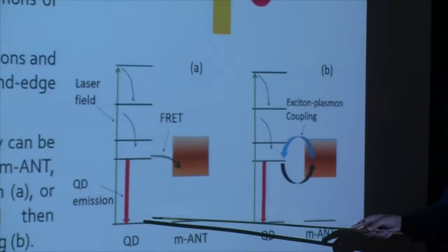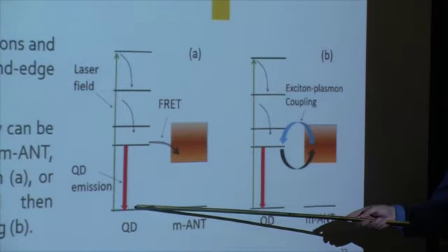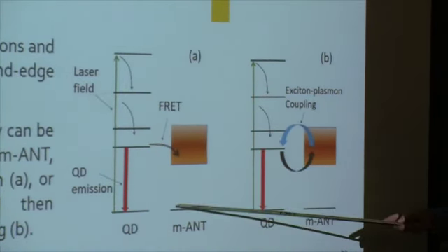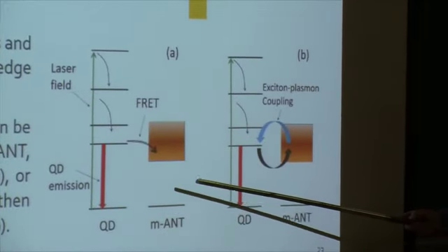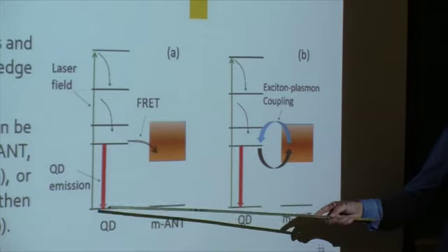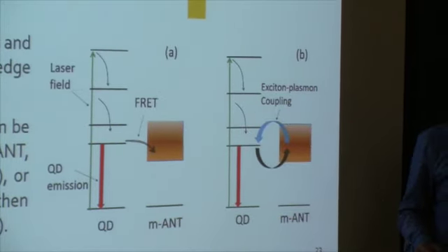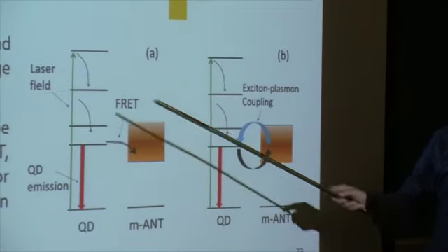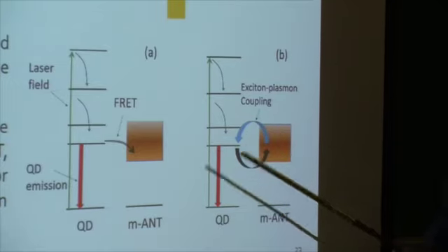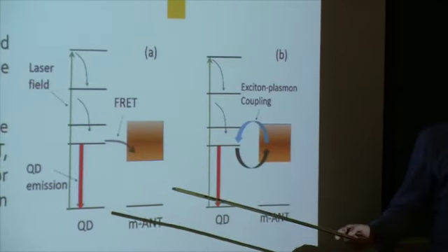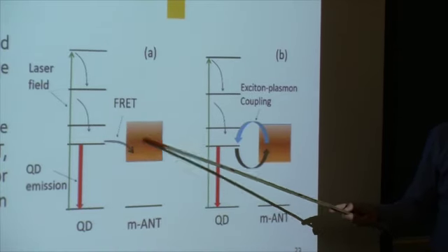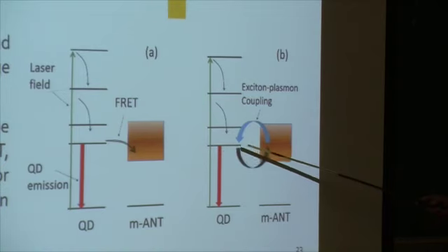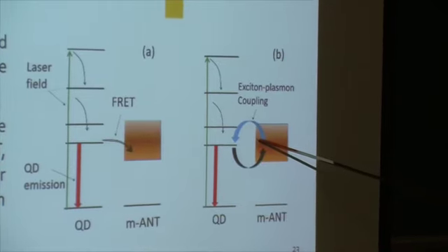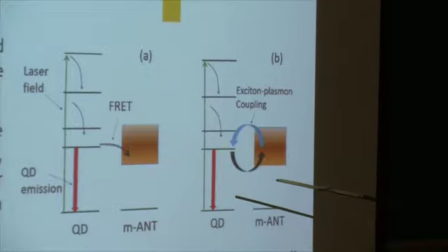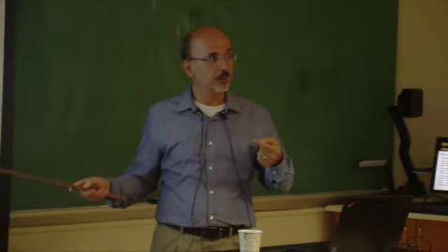So here is the story. This is the quantum dot transition states. This is the plasmon, a cartoon, a schematic of it. What we did, we send a light that excites only the quantum dot, not the metallic nanoparticle. What happens is that relaxation happens, and you have two chances. One chance is that the quantum dot can give up its energy through FRET, and this heats up. The other one is that the quantum dot can generate a field that excites the plasmon, and the plasmon in return excites the quantum dot again. This is quantum dot induced exciton-plasmon coupling.